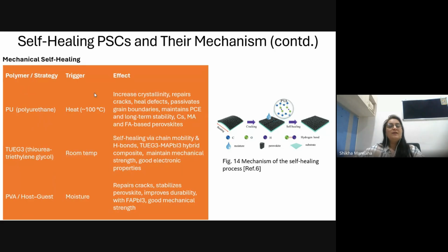Another is TUEG3, thiourea triethylene glycol. It triggers basically at room temperature. Here also it is acting as a self-healing material, in which there is a possibility that they can correspond to a proper mechanical strength, and they can also retain good electronic properties, the power conversion efficiency of the perovskite material, in a better way. Next is the PVA material. Again, its trigger is moisture, and it also has the capability to repair any cracks, to heal itself. And some of the works have been reported with formamidinium lead iodide.